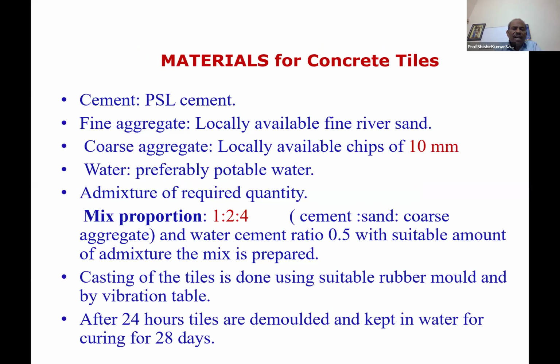Materials for concrete tiles: Portland slag cement. We have also done the same tests with OPC as well. First we have done slag cement, then we have done OPC, with fine aggregate. Mix proportion was 1:2:4. Casting of the tiles has been made using a suitable rubber mold and a vibration table. And locally available 10 millimeter chips were used.